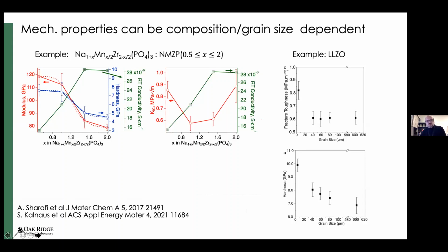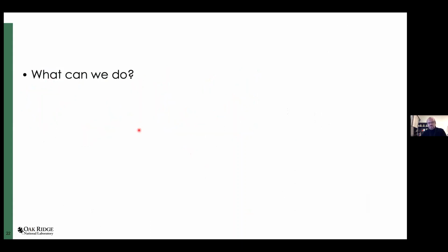Oh yeah, I need to mention that these properties, fracture toughness and elastic properties, very often depend on the composition and are connected with the ionic conductivity of the materials, as shown on these 2 examples, one for the LLZO garnet and one for the NASICON electrolyte. The nature of this dependence is still unknown, but it can fluctuate quite a bit depending on the composition of the material. So are things really that bad, and what can we do to make it a little bit more robust?